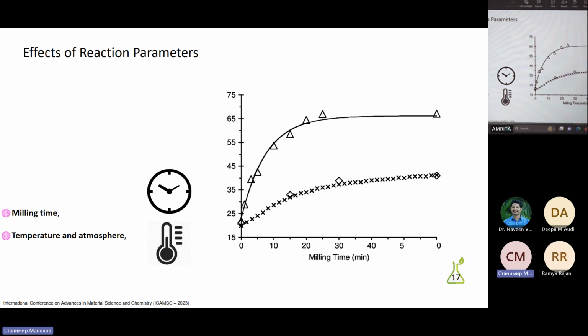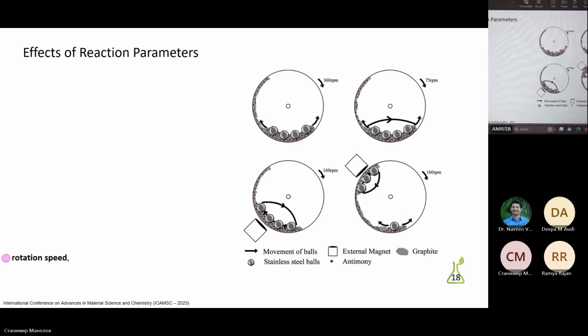The milling temperature is also an important parameter for mechanochemical synthesis, and to decrease the temperature, liquid nitrogen can be used on the milling container as well. If we would like to increase the temperature, electrical heating can be applied in the milling vial. Temperature changes directly affect the solid solubility levels and phase formation. The rotation or oscillation frequency affects the yield, selectivity, and similar properties of the reaction according to the kinetics of the reaction. If the frequency increases, side reactions occur, and this negatively affects the yield.